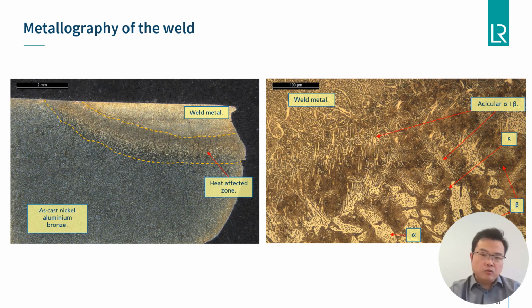As a comparison, we looked at the weld metal and the consequential heat-affected zone next to the cast material, also to understand the association of the weld with the properties of the propeller blade. The cross-section was taken through a weld along the fracture surface, highlighting the changes in microstructure after being etched using an etchant. The microstructural change in the heat-affected zone is very obvious.